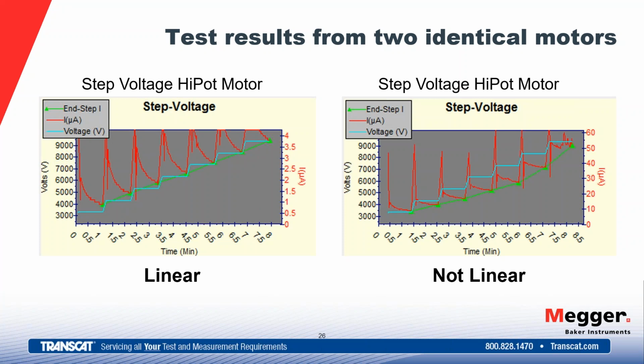This test passed. It didn't trip. Our minimum megohm values are still high, but it failed the nonlinear test. It's telling us that as we raise voltage on this, at some point our insulation is becoming weaker. The other indication here is that at this final step we do have instability in our current. So I would propose that the very next step would actually trip the tester at that point.